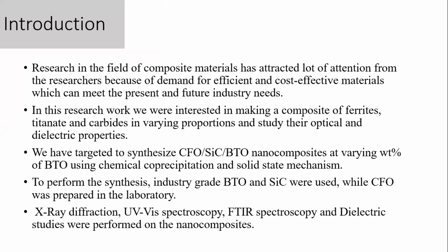As we know, research in the field of composite materials has attracted a lot of attention from researchers because of the demand for efficient and cost-effective materials, which can meet the present and future needs of industry. In this research work, we were interested in making a composite of ferrites, titanates, and carbides in varying proportions and studying their optical and dielectric properties. So we targeted to synthesize cobalt ferrite, silicon carbide, and barium titanate nanocomposites at varying weight percentage of barium titanate using chemical coprecipitation and solid state method. To perform the synthesis, we used industry-grade barium titanate and silicon carbide, while the cobalt ferrite was prepared in the laboratory. For characterization, we characterized our samples of nanocomposites for X-ray diffraction, UV visible spectra, and FTIR, and dielectric studies were also performed.